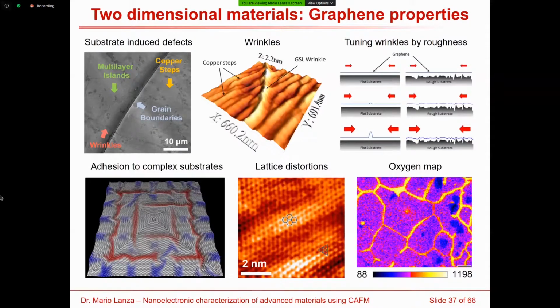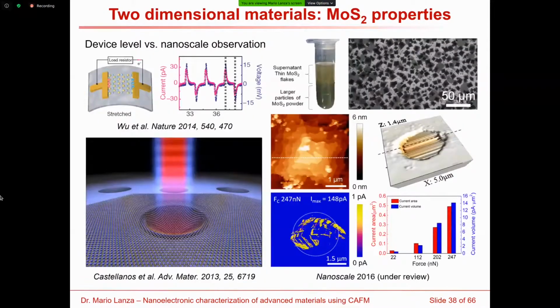But then I decided to apply the conductive AFM to analyze some properties of 2D materials. And as I mentioned before, the conductive AFM is unique because it allows us to measure at the same time mechanical and electrical properties at the nanoscale. So in 2014, I saw a paper in Nature in which it was demonstrated that molybdenum disulfide is a piezoelectric material. And it was demonstrated at the device level